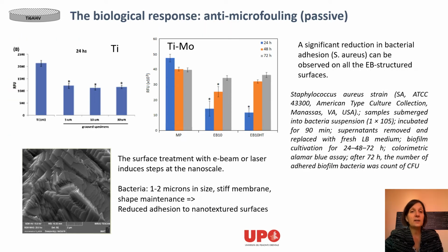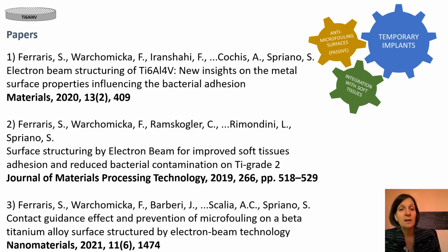And here you can see on different titanium-based materials, the beta titanium alloy or pure titanium, that there is this anti-microfouling action. So there is a reduced amount of bacteria because of the steps on the surface. And this can be explained considering that the bacteria have a stiff membrane and they are very large in dimension, so they want to maintain their shape, and it is difficult to do this on such a surface, so there is a reduced adhesion of the bacteria on the nanotextured surfaces. And some papers about this topic if you are interested in this.